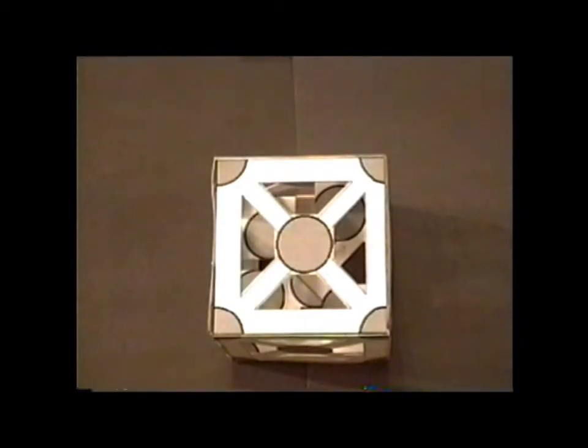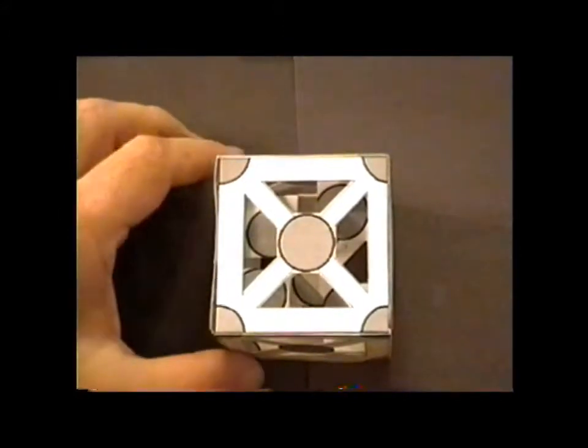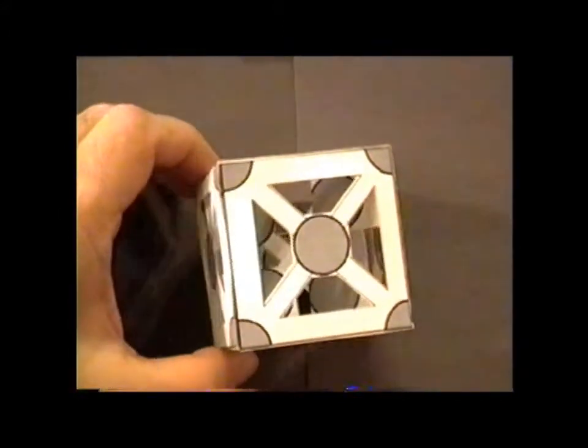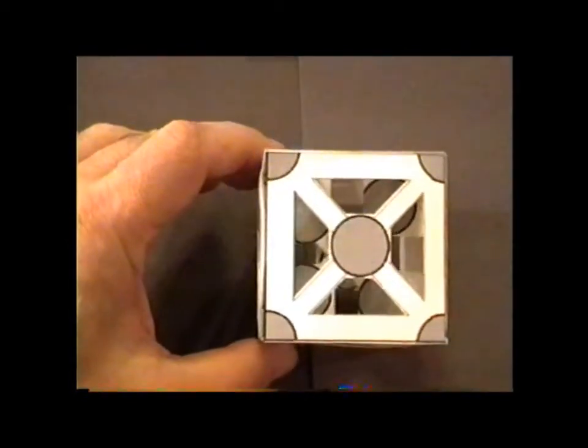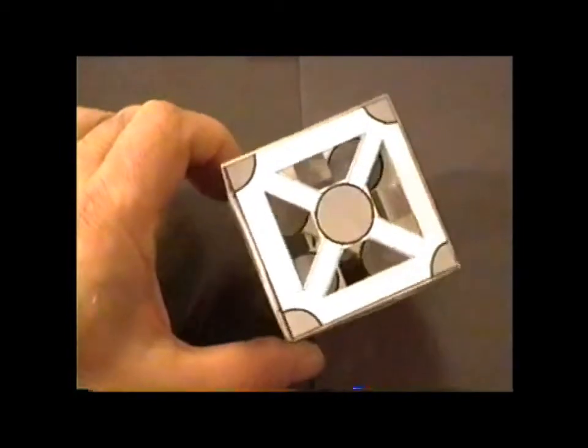One of the important structures derived from face-centered cubic is the diamond structure. Diamond is exactly the same as face-centered cubic, but we have half of the tetrahedral holes in the lattice filled, again with the exact same element that is found at each vertex and at the center of each face. We tilt it slightly around this way and start to see where the additional atoms are at the tetrahedral holes.